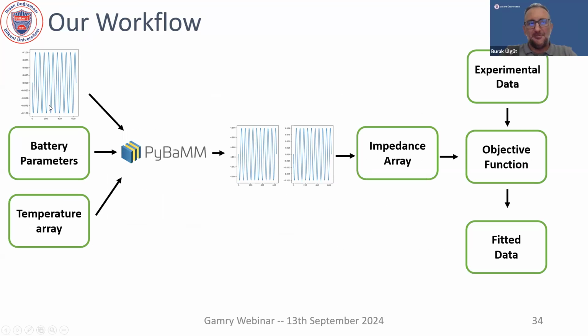So we take our signal, we use our battery parameters, we use our temperatures, throw them into PyBaMM. We calculate voltages at every frequency, at every temperature, and for every nonlinearity. And then we calculate the impedance. And then we compare experimental data with the impedance with an objective function to minimize, and we do the fit.